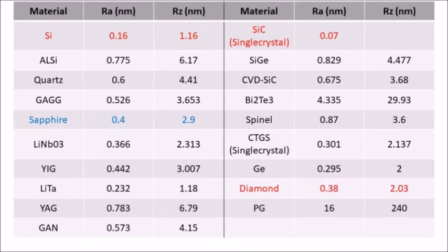This is the list of semiconductor items, and we have polished 19 materials. Single crystal SiC has the best roughness, which is Ra 0.07 nanometers. Also, silicon has a good roughness, Ra 0.16 nanometers and Rz 1.16 nanometers. We can achieve Ra 0.38 and Rz 2 nanometers with diamonds. This diamond was also single crystal.